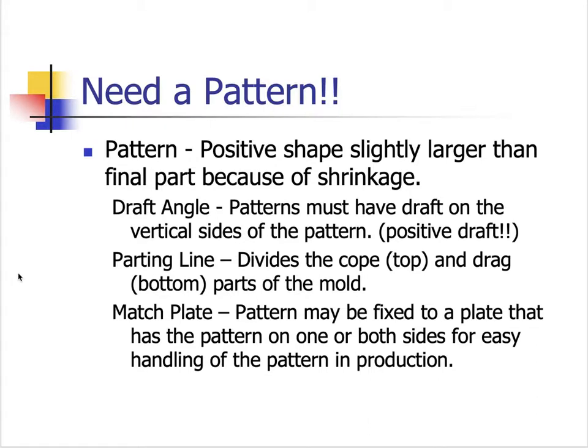So generally, a pattern is usually a positive shape when we're doing sand castings, especially green sand castings, and you need a positive shape slightly larger than the final part. And what happens is, as metal cools, it will tend to shrink. And what I mean by that is the bar starts out, or something I'm casting starts out at 12 inches. After you cast it, it's going to be some distance smaller. And the reason for that is, as it cools from a high temperature liquid to a low temperature solid, it shrinks a little bit.